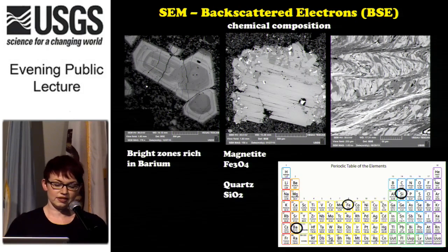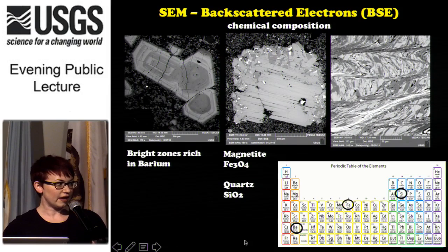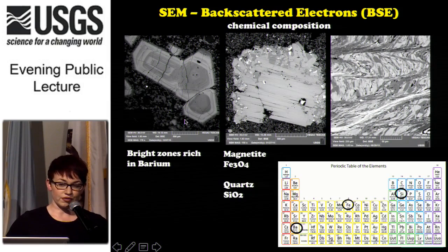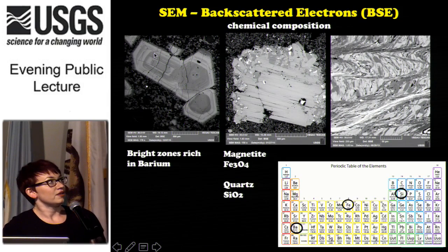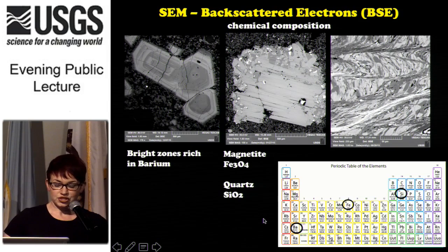Our other detector is backscattered electrons, or BSE. This gives us information about chemical composition. It works on the premise that the higher the atomic number, so the farther down it is on the periodic table, or the heavier it is, the brighter it looks in BSE. So here in this first image, this is a sanidine mineral grain from the Hayes volcano in Alaska. These alternating bright and dark zones are barium rich. So you can see barium way down here. It's pretty heavy in terms of the periodic table, so it shows up brighter.